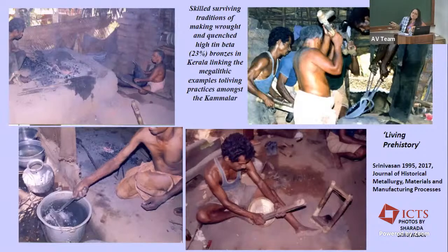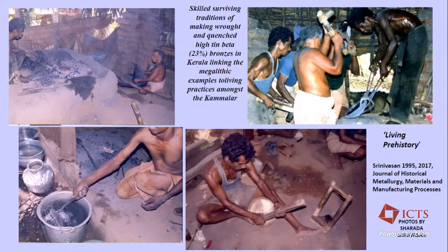And I was also able to find some traditions where they're still working high-tin bronzes in exactly the same way. This was in Palakkad in Kerala. So it shows you here how first the cast ingot of 23% beta bronze is being annealed here. And in fact, in those days, they were using these buffalo-back bellows, which are no more used. I guess they've gone to modern bellows and so on. And then it is hot forged on the stone anvil in repeated cycles of annealing and hot forging.